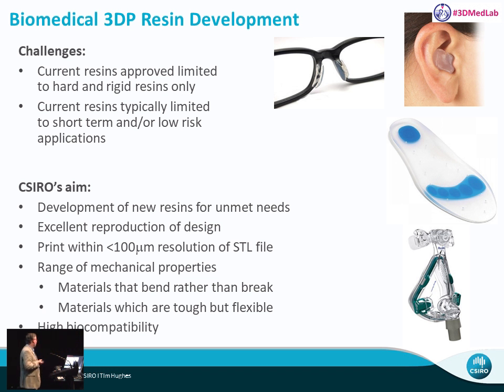So we've been trying to develop resins for biomedical applications. There are commercially available materials for this already, but the challenge is that many of them are really rigid and hard. As a result, they fail catastrophically, and they'll break rather than bend. The other problem is that these types of materials are typically only approved for short-term use or low-risk applications. So our aim was to develop improved materials to address some of these unmet needs.